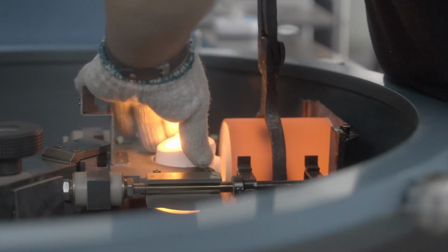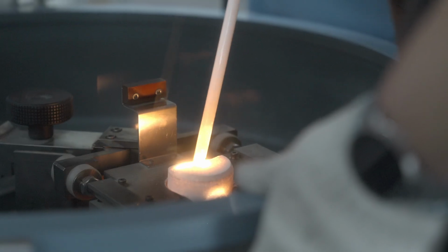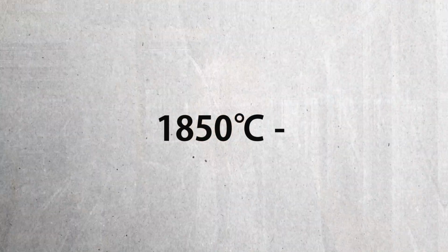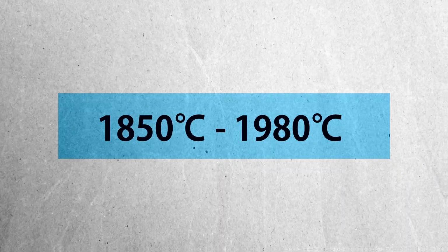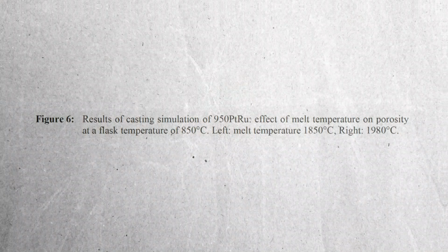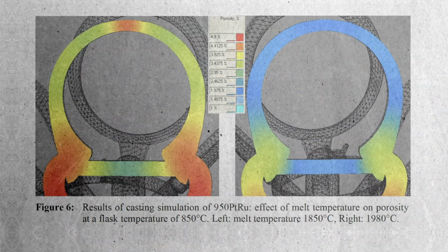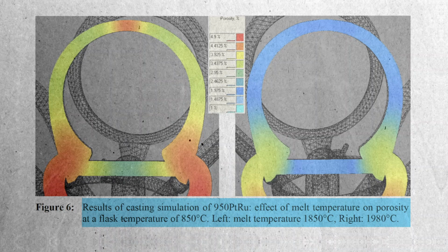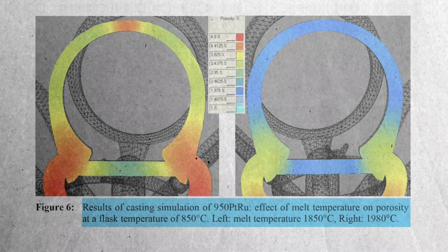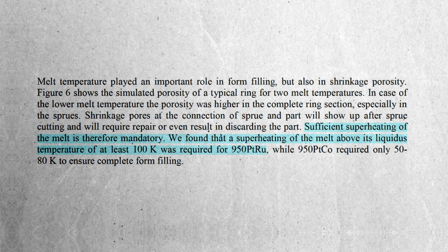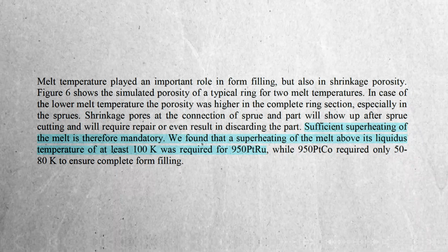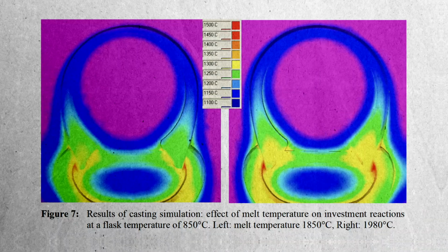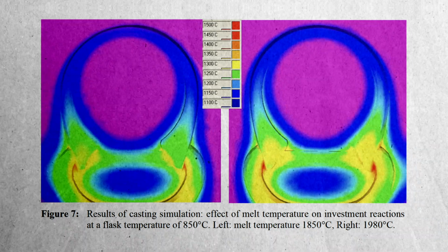Great. I only wish it was that simple when it comes to the melting pour temperature of the platinum stuff. Dr. Klotz did give us a reference and a range for platinum ruthenium, and it was between 1850 and 1980 Celsius. There are diagrams showing results from the two different temperatures. Figure 6 is a casting simulation on the effect of melt temperature on porosity in platinum ruthenium. Different melt temperatures can yield different porosity results. On the other hand, figure 7 shows the effect of melting temperature on investment reaction.